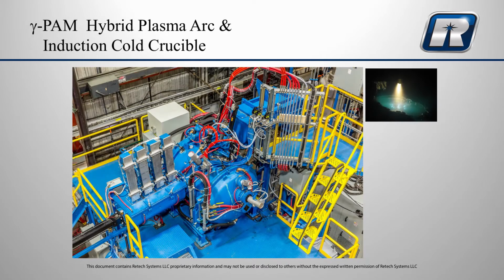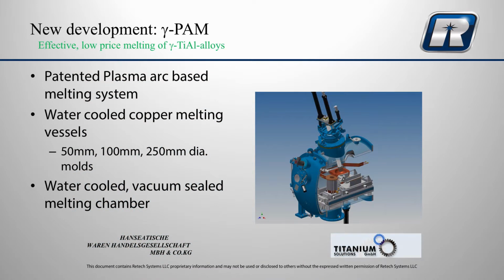As I mentioned, Gamma PAM is a hybrid system between plasma arc and induction melting. In this system, the main melting chamber is in the center. Off to the left is one of the feeding systems where the briquettes are loaded into the vertical towers. In this system, the customer specifically wanted the ability to remelt powder. So on the right is a rotary feeder with a vibratory mechanism that will feed the powder directly into the ingot withdrawal mold. Schematically, the Gamma PAM looks more like the system shown in the cross section here.